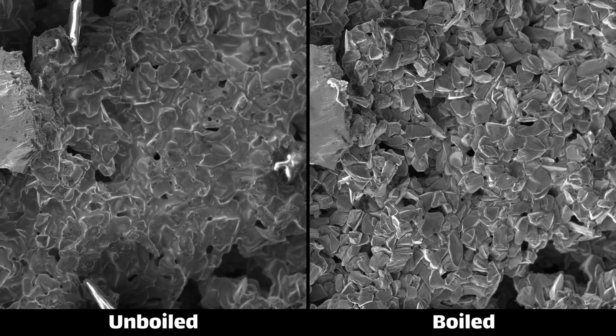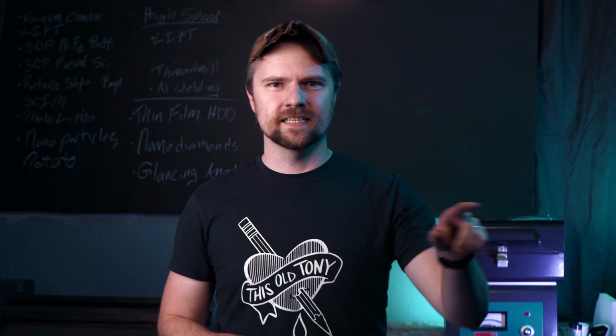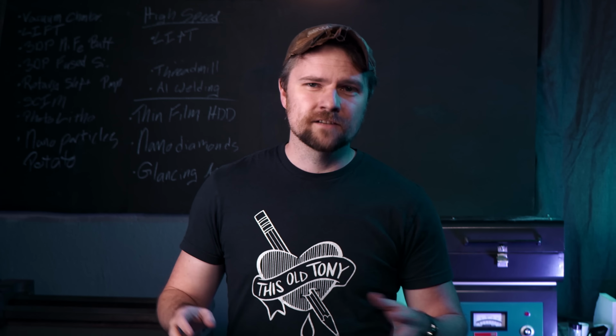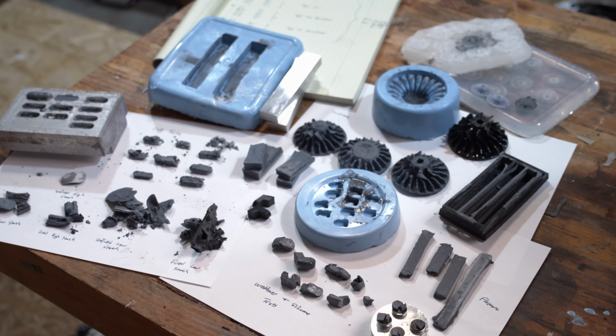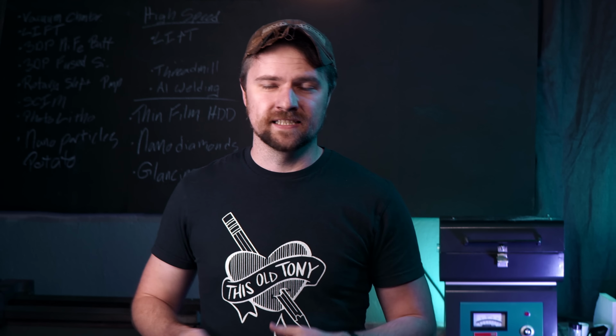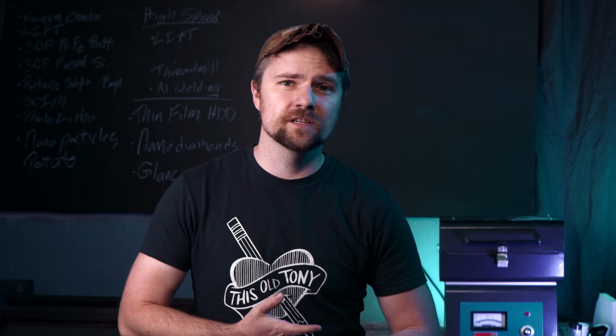This variability was maddening to me because I couldn't get it consistent enough to really definitively say, yes, this is what's going on. So I did repeat this a bunch of different times, and essentially the end of the story is that in some cases, the morphology changes when you boil it, and in some cases it doesn't.